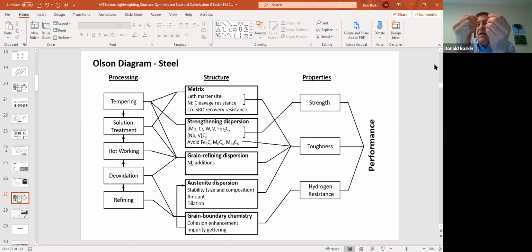The tempering is the precipitation hardening. So steel, like aluminum, doesn't always, but can strengthen through precipitation hardening. These are the different processes that you use in order to make a steel. But these processes dictate or translate directly into different features in the microstructure. A lath martensite is one of the highest strength materials there is.